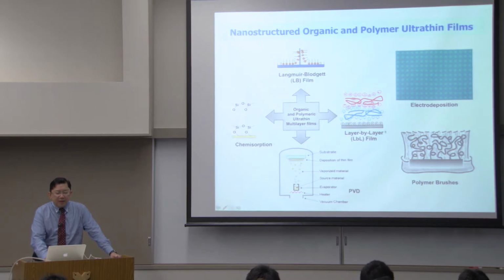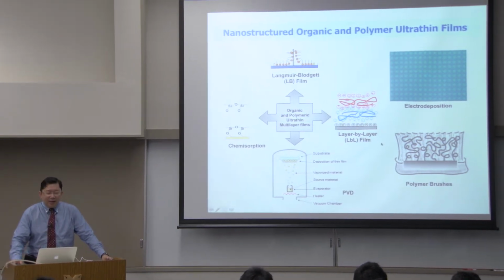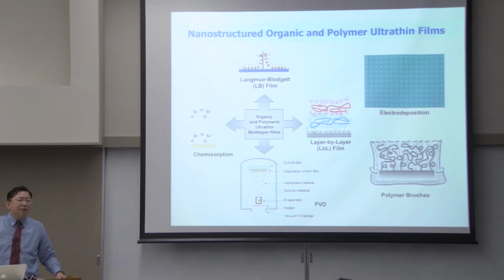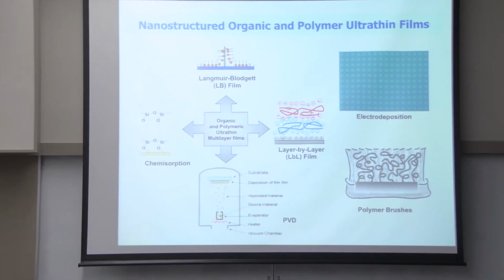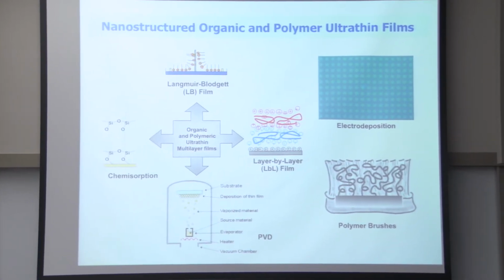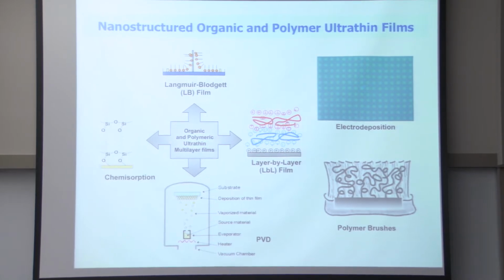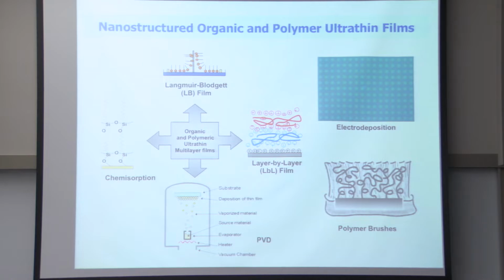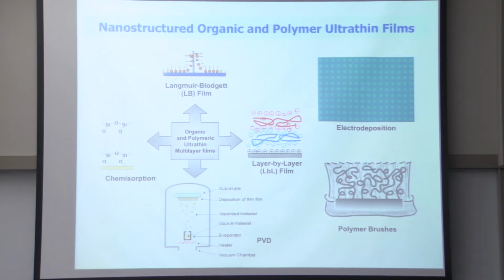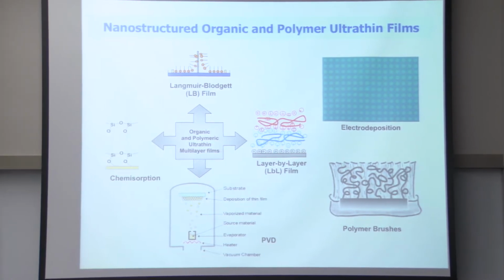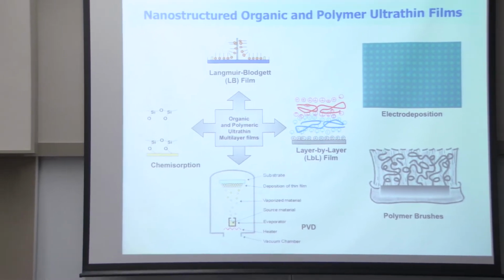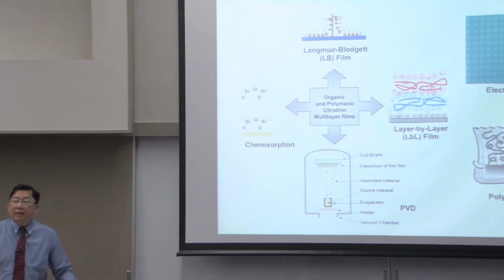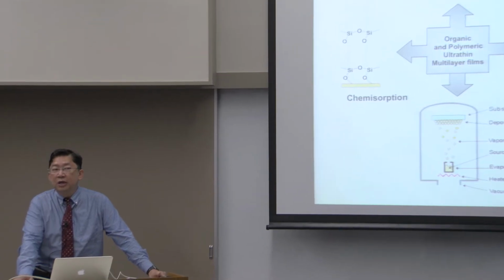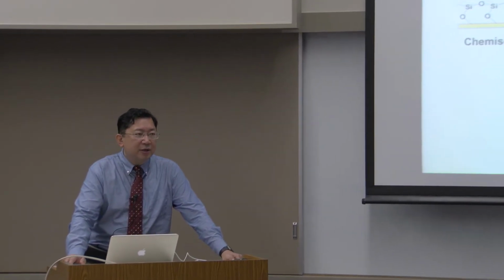Another method is by the use of polyelectrolytes. Polyelectrolytes can adsorb on surfaces where you have opposite charges; if you have the same charges, it will repel due to electrostatic repulsion. Because of ion exchange, you build up layers pretty quickly simply by alternating negative and positively charged polyelectrolytes, nanomaterials, or even amphiphiles.